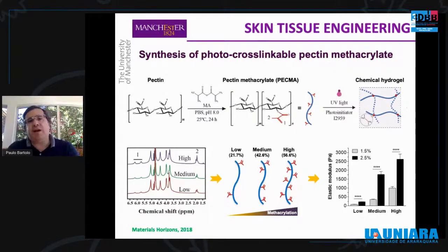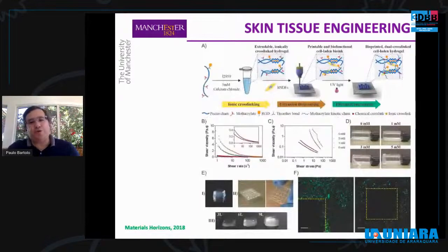We focus also on a photo-curable additive manufacturing approach. So first of all, it was necessary to functionalize pectin. We have done that using methacrylic anhydride, and we consider different levels of functionalization, different levels of methacrylation to create pre-polymers with different rheomechanical properties. And then we prepare a protocol to print this bio-ink.